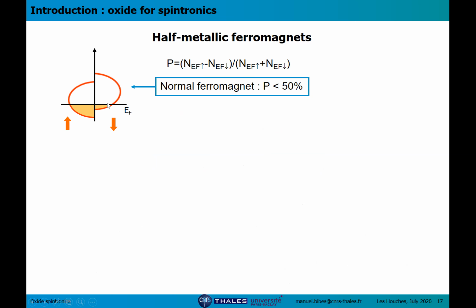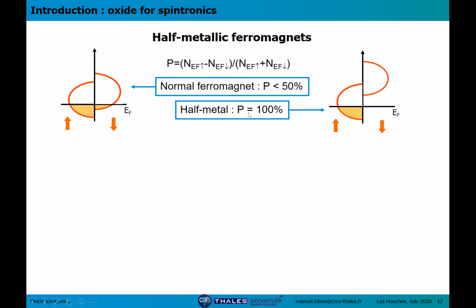So this is the density of states of a normal ferromagnet. You have states present at the Fermi level for both spin up and spin down with a given imbalance. In this case, for instance, you will have a spin polarization of maybe 50%. However, if you have a different band structure, maybe a larger exchange splitting or more narrow bands, you can have a total spin polarization of the density of states, meaning that you have states available at the Fermi level just for one spin direction, here spin up, and there's a gap for spin down.